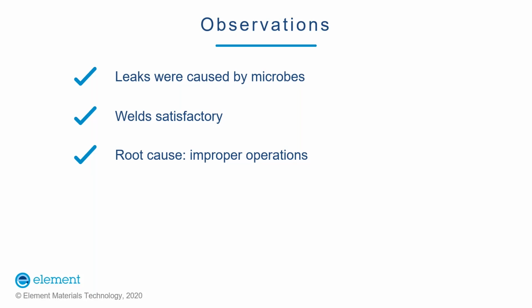The bacteria that was present in the hydrotest water preferentially attached to the internal surface of the pipe, especially on the weld metal, due to more surface roughness and grain boundaries as compared to the base metal. Over the period of time, bacteria attack the metal and cause leakages.